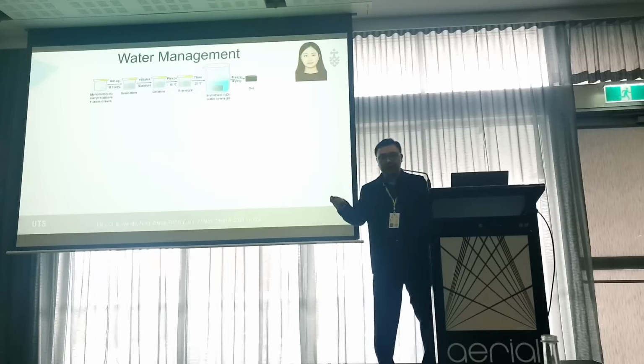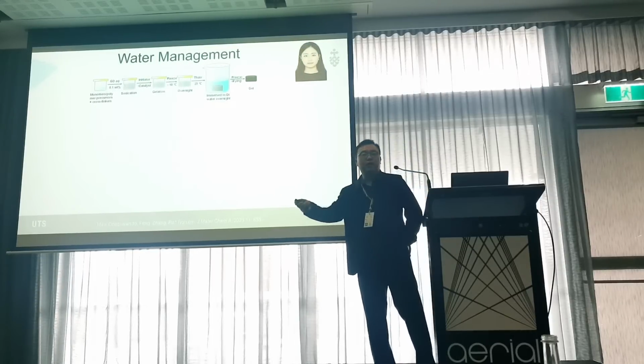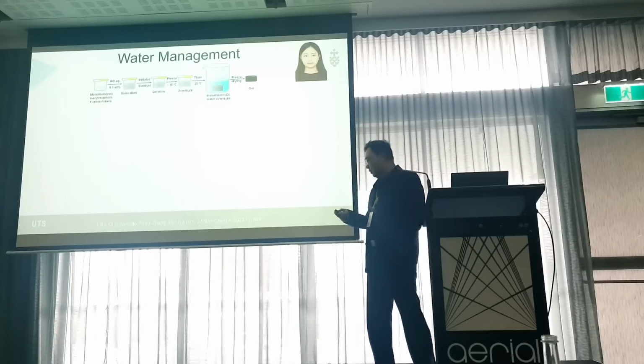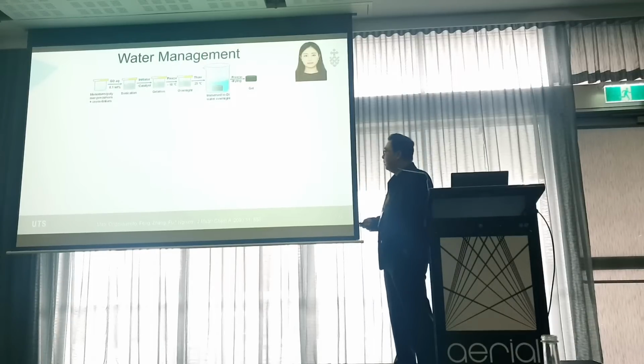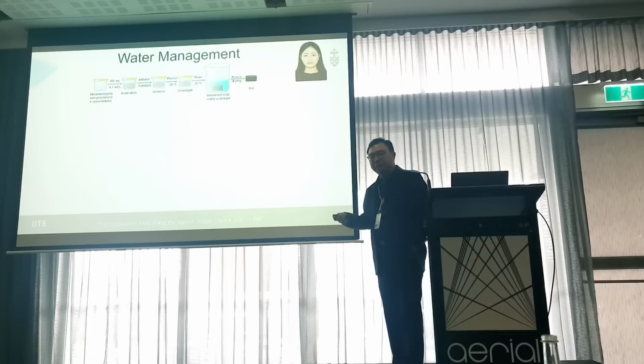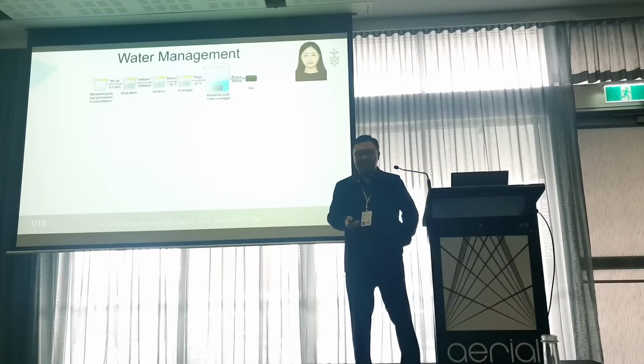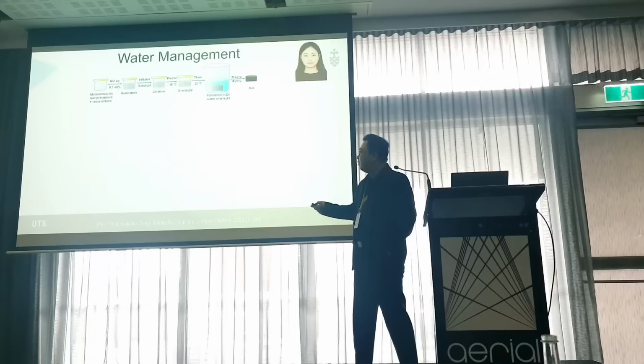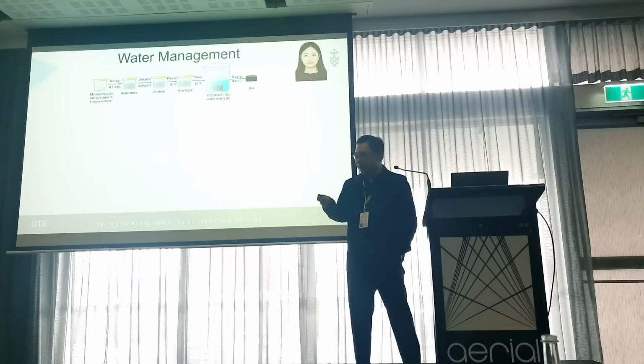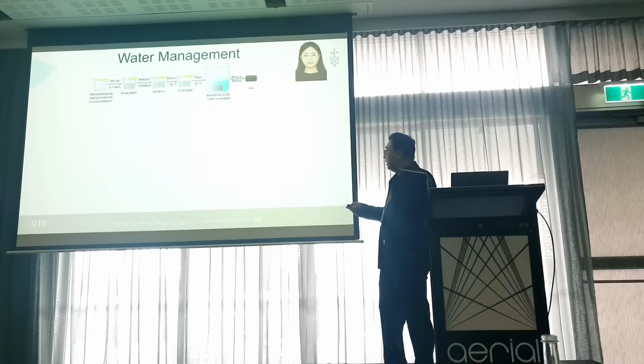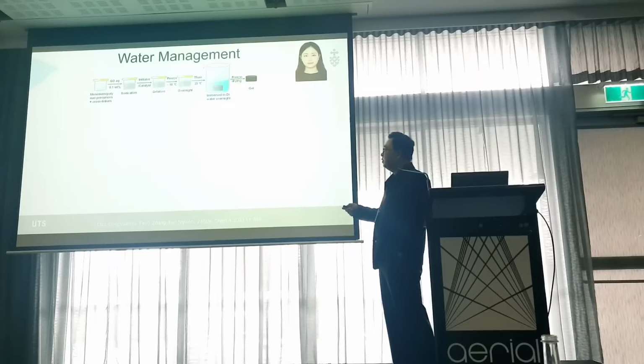At the same time, our research also focuses on water management strategy, and my student Shudi conducted this work. In this study, we use graphene oxide because graphene oxide is relatively cheaper, and we can buy 1 gram of it. That's why I chose to use this 2D photothermal material instead of porphyrin nanosheet. And we use only 0.1 weight% graphene oxide as the photothermal material.